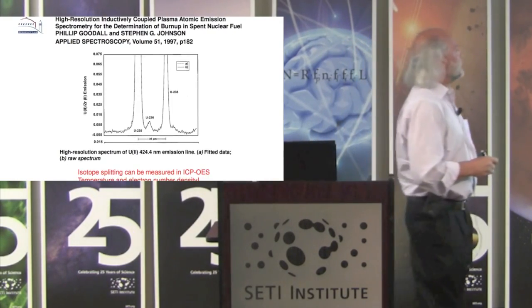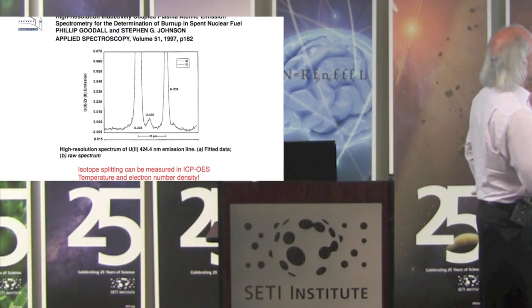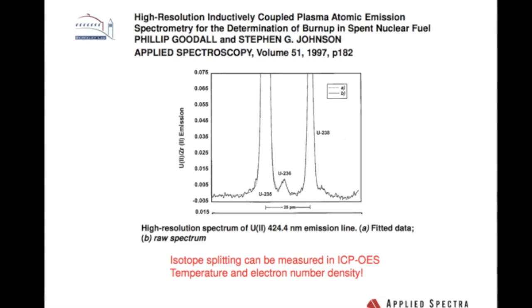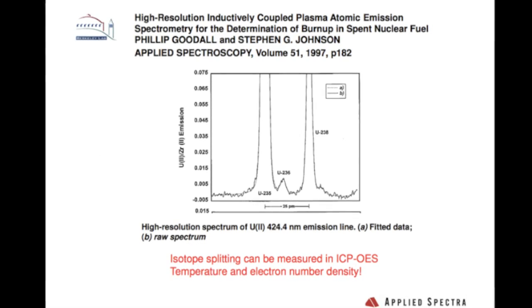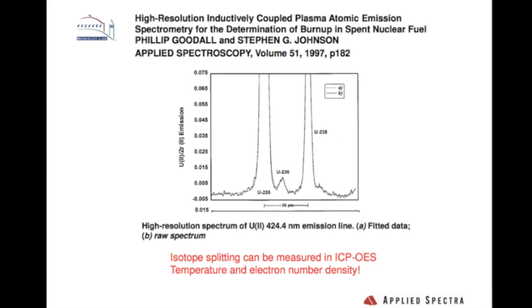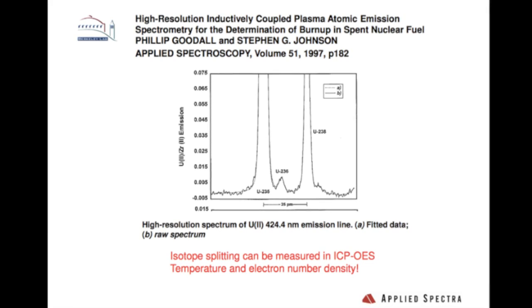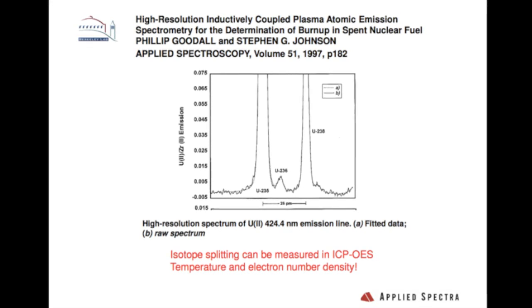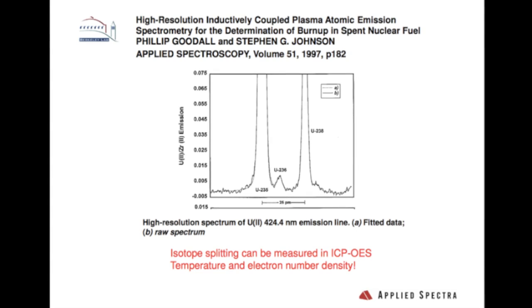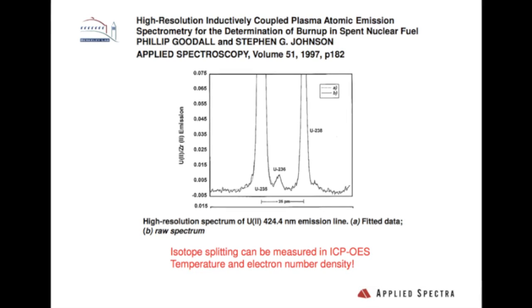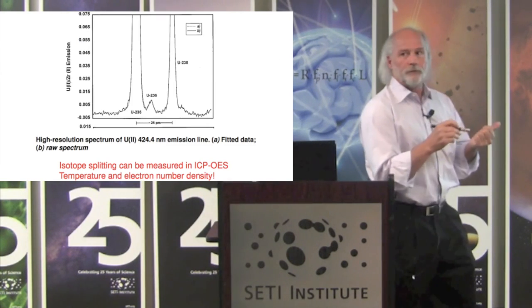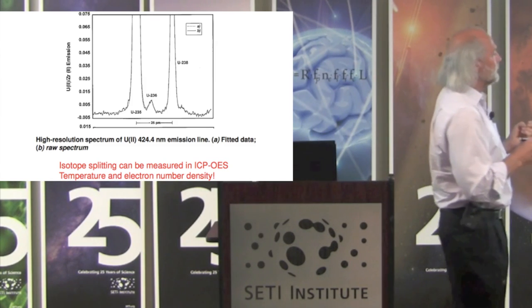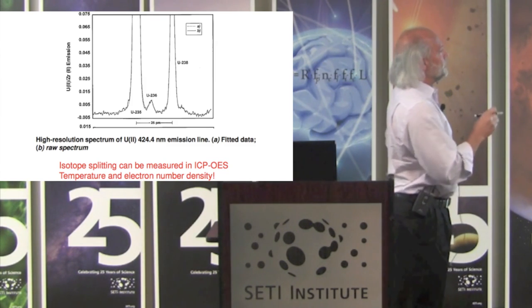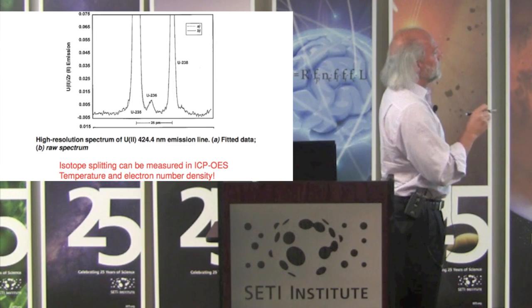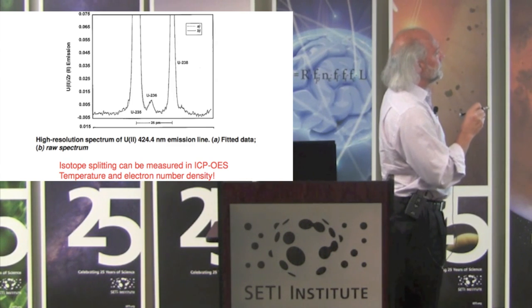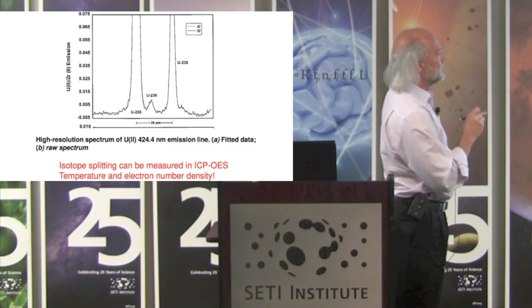So let me just give you an example of what people have been able to do with ICP-OES. This is where they actually sent samples into the inductively coupled plasma and looked at the emission spectroscopy. OES is optical emission spectroscopy. Some people say atomic emission spectroscopy, AES. But anyway, this source is a plasma, and it runs at a much different temperature and electron number density than a laser plasma. But people have been able to see the uranium 235, 236, 238 isotopic shifts.